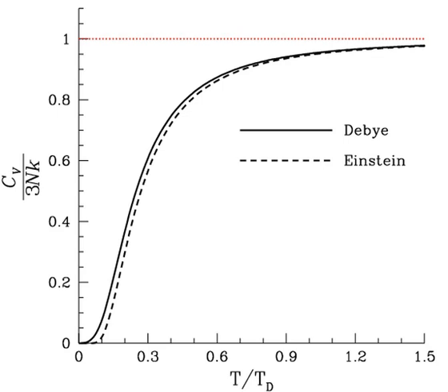This limit of 3R per mole specific heat capacity is approached at room temperature for most solids, with significant departures at this temperature only for solids composed of the lightest atoms which are bound very strongly, such as beryllium, where the value is only 66% of 3R, or diamond, where it is only 24% of 3R. These large departures are due to quantum effects which prevent full distribution of heat into all vibrational modes, when the energy difference between vibrational quantum states is very large compared to the average energy available to each atom from the ambient temperature.